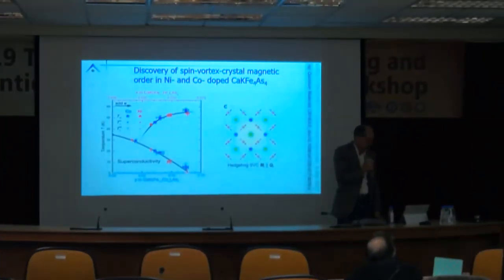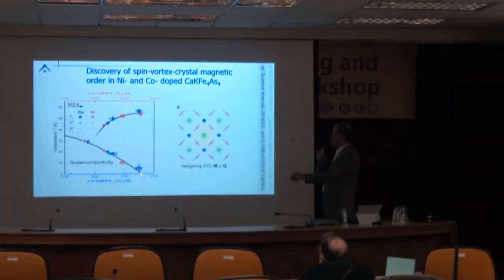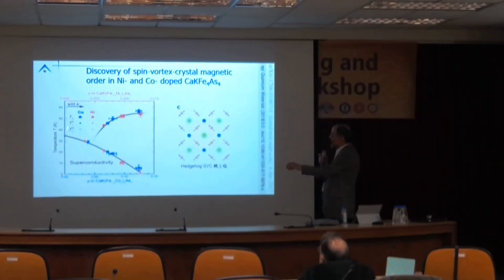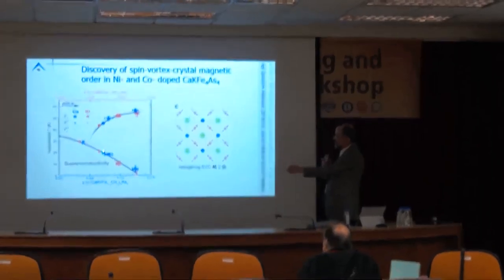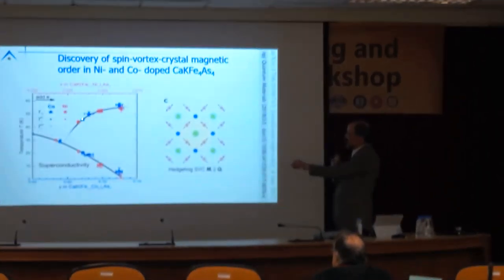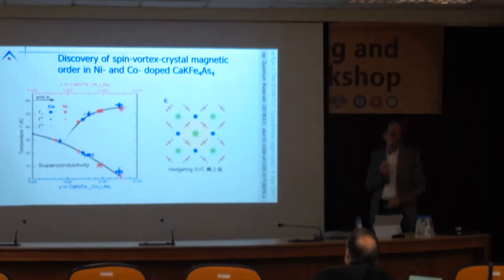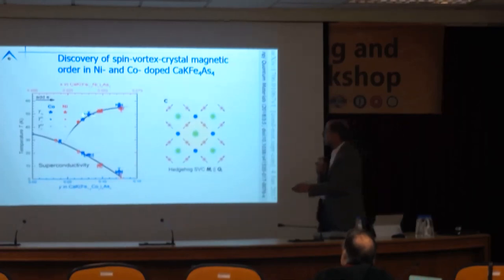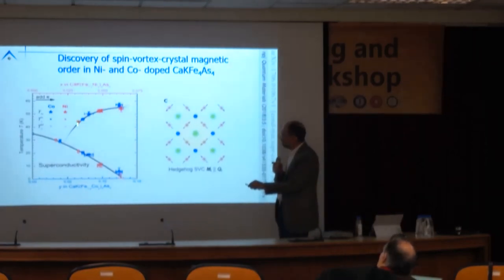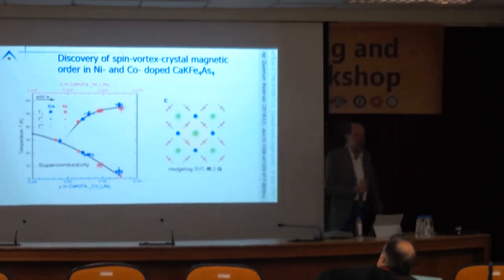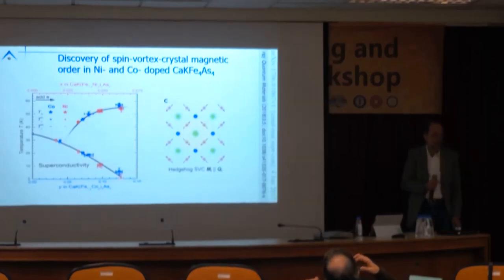You mentioned this non-collinear antiparallel order in CaKFe4As4. Is it also a superconductor? Oh God, yes. Let's be careful. So here's our phase diagram. The pure material is away from this magnetic phase field. On the other hand, as we substitute in nickel or cobalt, we still have superconductivity and we have our spin vortex crystal, like underdoped barium 122 with cobalt and potassium. In this case, we have this 2Q hedgehog structure. And when we do both neutron scattering and Mössbauer, we can see that as we bring these close together, our order parameter takes a hit and decreases as we drop into the superconducting state, something we observe pretty well in cobalt and nickel substituted barium.